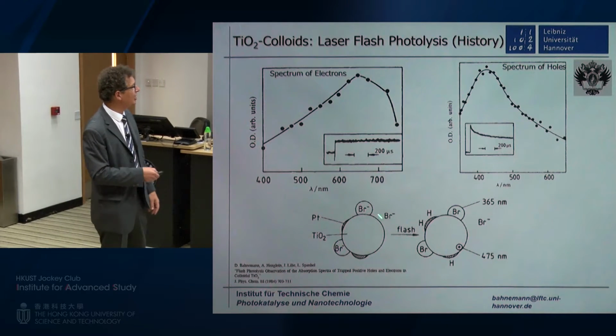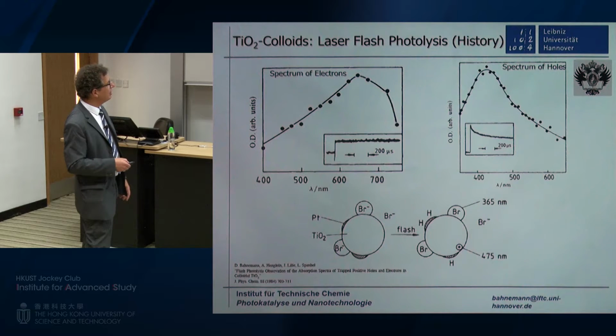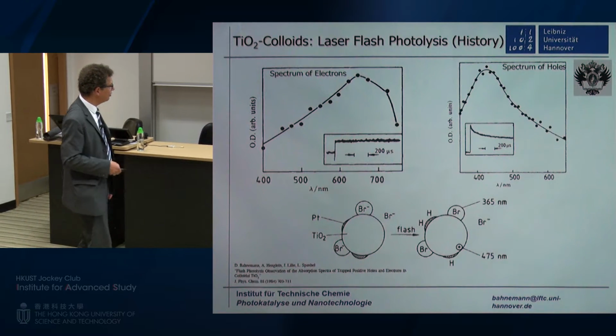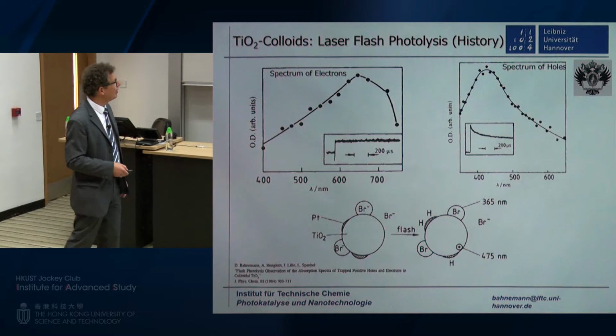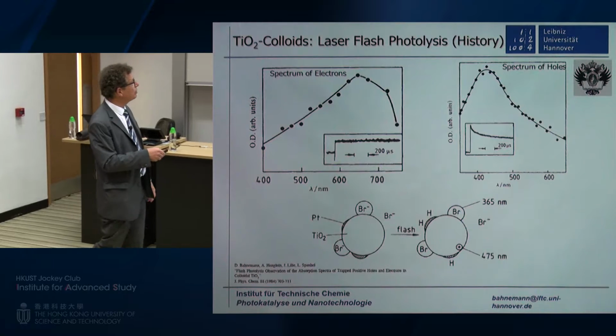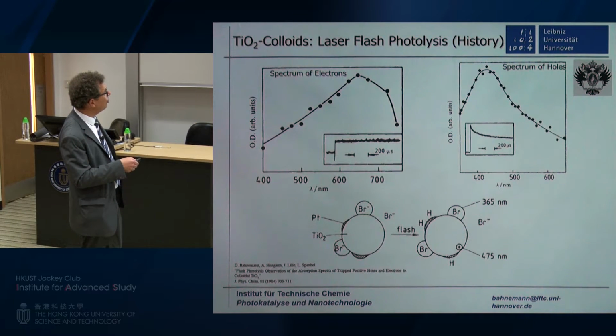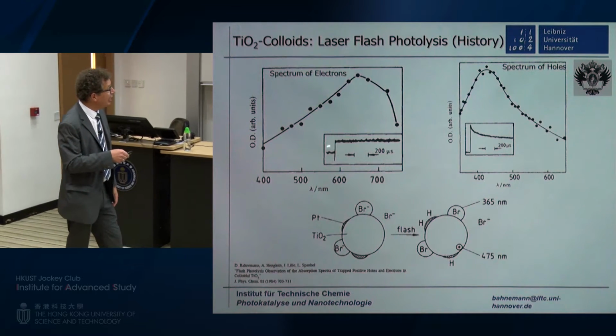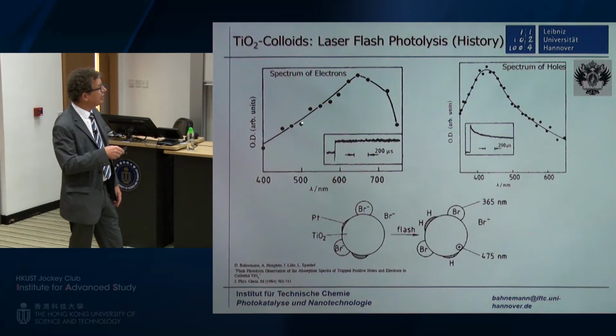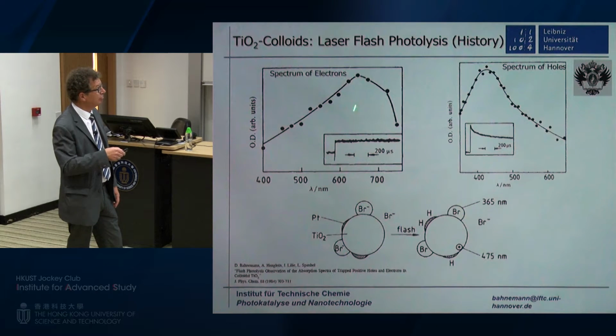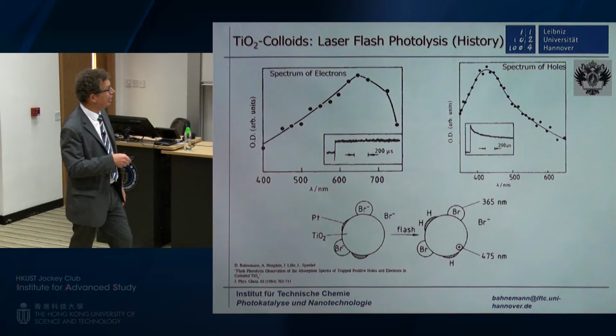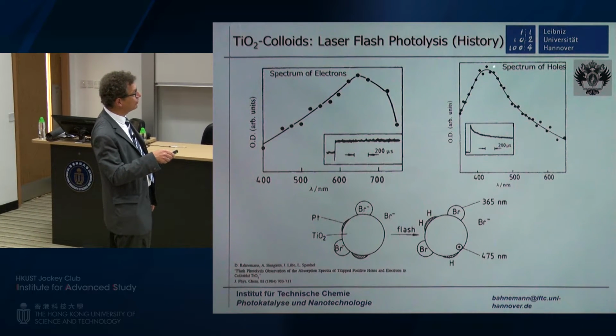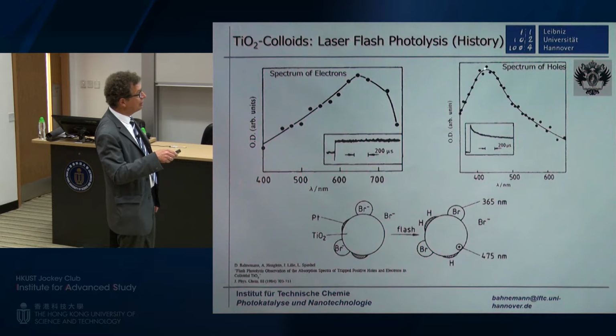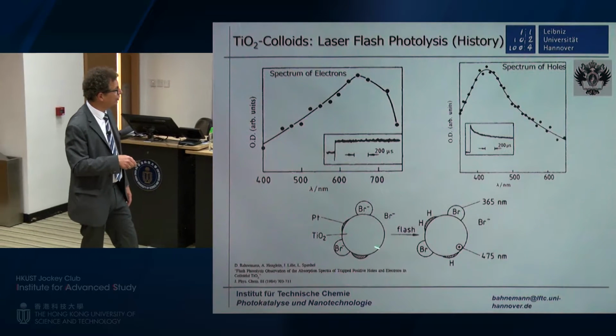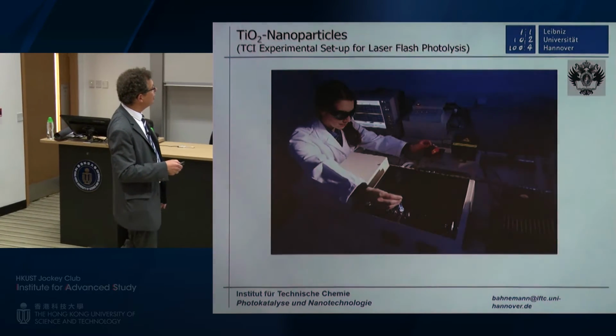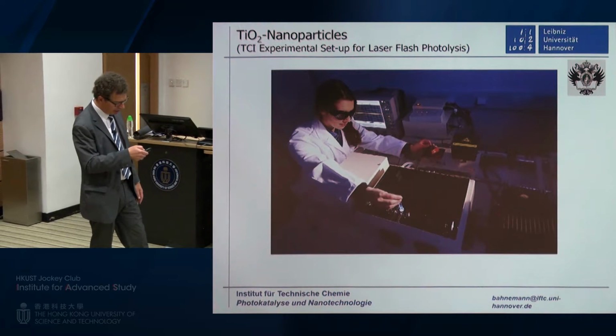As a young postdoc, I started doing laser flash photolysis work on TiO2, paper published as early as 1984, so well over 30 years ago. We published this paper in my early postdoc studies before I even joined Caltech, and we saw the spectrum of the electrons. I've shown you this already, very stable in the absence of oxygen, and we also saw a spectrum of the holes at around 400 nanometers, and we looked at the reactions of these beasts. This is very old history, and this is my young colleague, Jenny, at work.